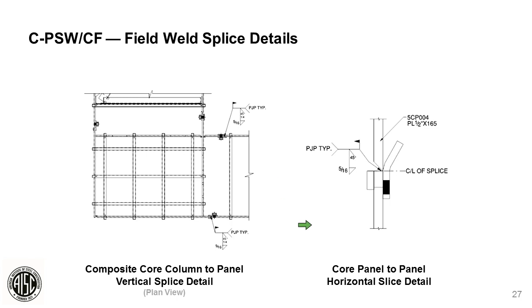If we look at the chosen weld that was proposed for this project by the fabricator or the erector, this field weld was pre-qualified through testing to validate that it was a capacity weld where we were not failing the weld and we were delivering the full capacity of the plate and yielding the plate outside the weld. So this was a full depth PJP weld with a reinforcing fillet sized in order to develop the capacity of the plate. This PJP weld was chosen by or suggested by the erector mostly because of the field inspection requirements.